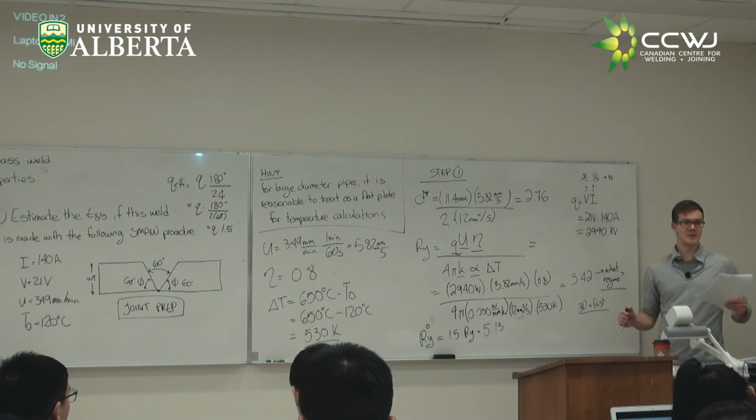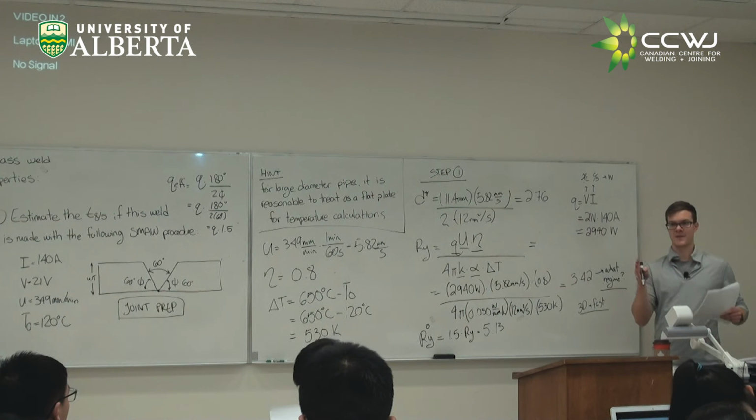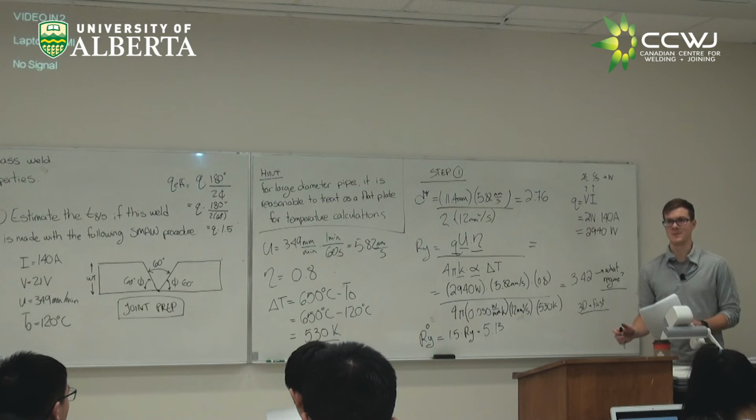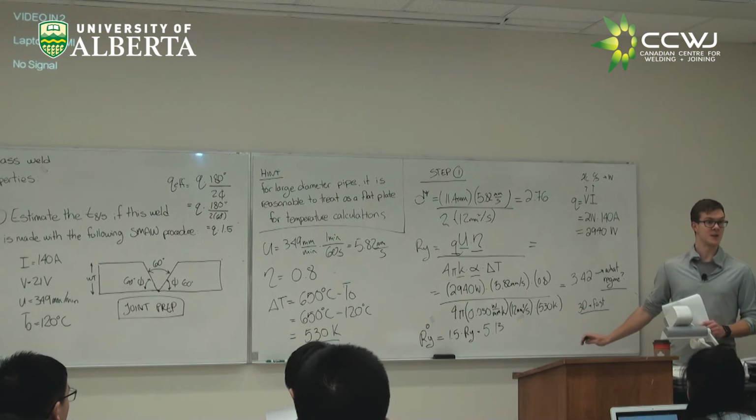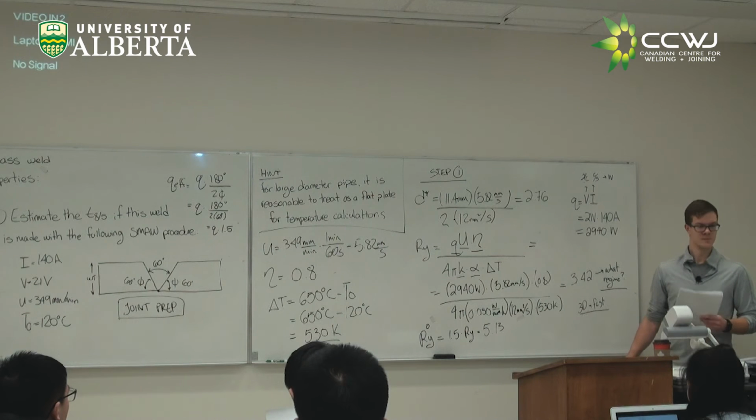So we're right on the edge there. But what that edge is really describing is where the 3D equations and the 2D equations would predict the same result. So if we're right on the edge, I'm going to suggest we're going to be okay to use our thick plate approximation.